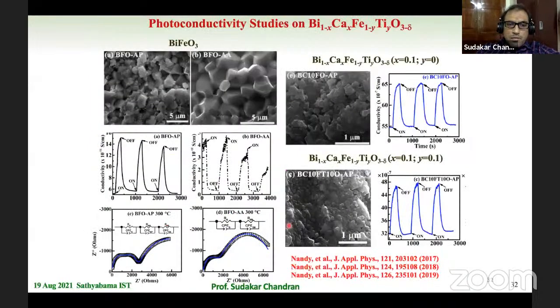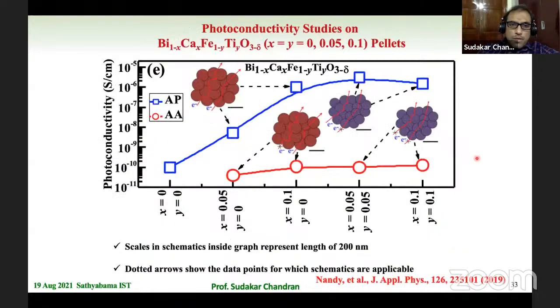So we were interested in this aspect, and therefore explored the photoconductivity properties, and the photoconductivity properties of these calcium and titanium doped BiFeO3 are very promising, and we have done extensive study on these compounds. I will just tell the gist of it. So basically, the defects that would reside mostly in the grain boundary regions, and also that come from the calcium and the titanium doping seem to play a very important role in deciding the photoconductivity.